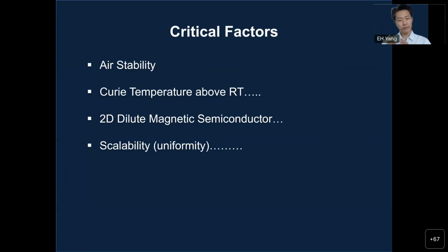So I would say there were four critical factors. One is air stability to some extent. If your materials are put in ambient conditions and they're gone in an hour, that's going to be a problem. So a lot of researchers have to use a glove box, and you have to manipulate these materials and stack them in the glove box, and you have to really package them. You have to encapsulate the materials with hBN and so on and so forth. Otherwise, the materials will be gone in a matter of hours, days, or weeks. So air stability is important.